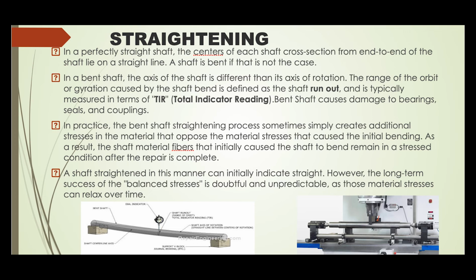A bent shaft causes damage to bearings, seals, and couplings. In practice, the bent shaft straightening process sometimes simply creates additional stresses in the material that oppose the material stresses that caused the initial bending. As a result, the shaft material fibers that initially caused the shaft to bend remain in a stressed condition after the repair is complete. A shaft straightened in this manner can initially indicate straight.